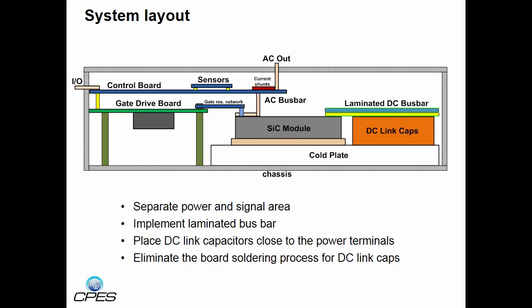Here's a look at the system arrangement. On the left, we have the signal input to the control board, where the sensors are mounted. The SiC gate drivers are located underneath the control board, and gate resistor boards are used to interface to the silicon carbide power modules. The modules are on a cold plate which has 70 degree C liquid cooling. The laminated DC bus bar is shown on the right, where it can be seen that the DC link capacitors are mounted to the underside of the bus bar and rest on top of the cold plate.